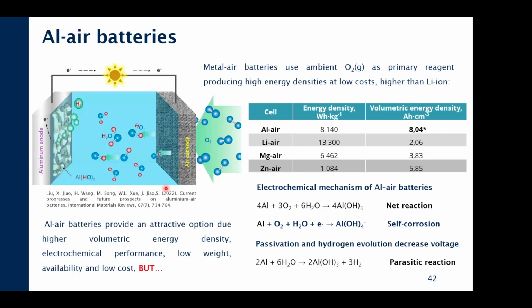For example, in metal air batteries, the idea is to corrode the metal anode, in this case aluminum, and we put it in front of an air cathode and some necessary electrolyte to get the electrical energy from the oxidation of the aluminum. So you can see that controlling the corrosion rate in this case is also important to produce a high energy density. Theoretically, aluminum air batteries are one of the best in terms of volumetric energy density. But the problem is that self-corrosion and also the parasitic reaction that produces hydrogen inhibits getting the most out of these batteries in terms of electrical discharge.